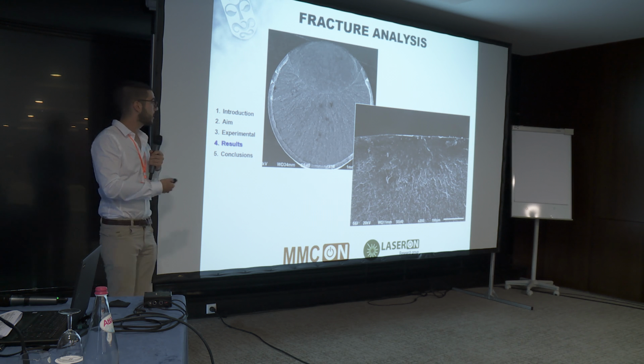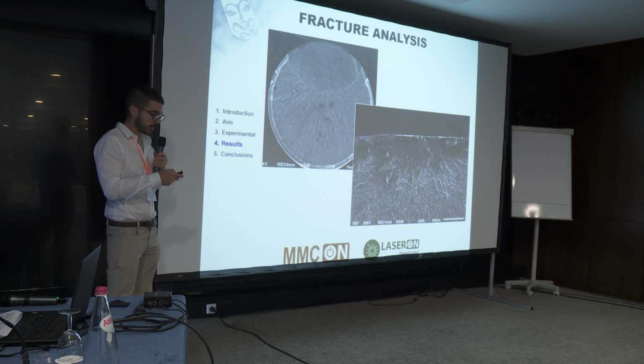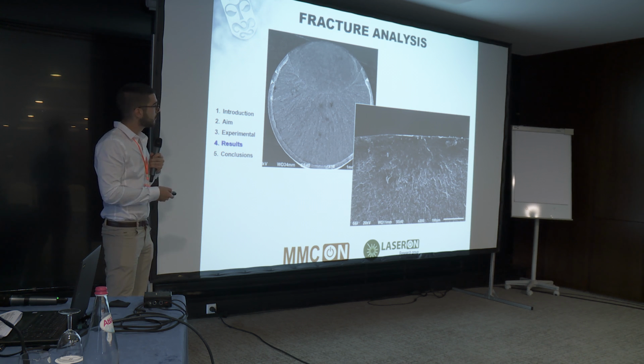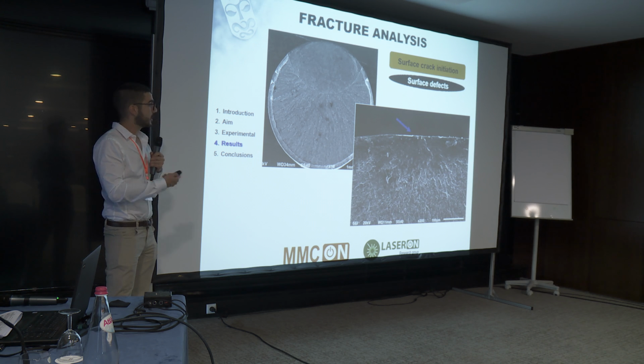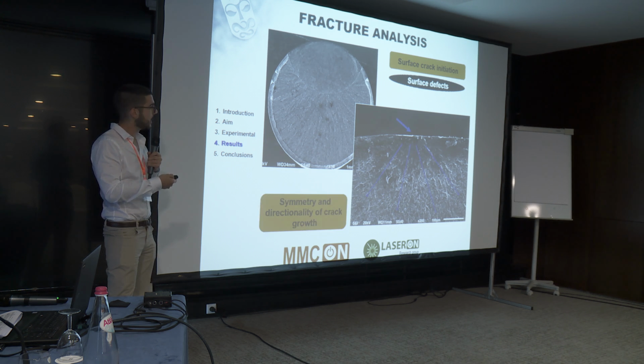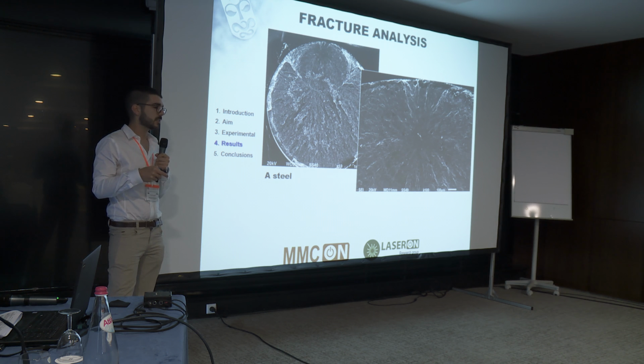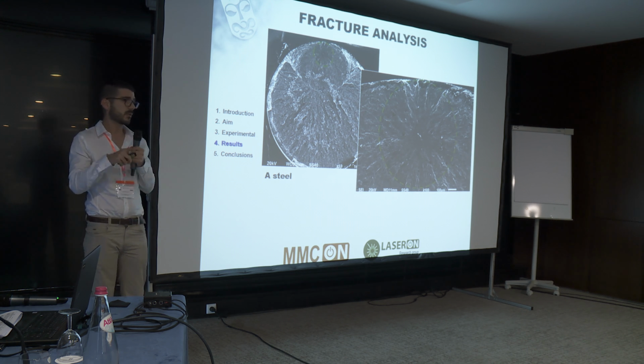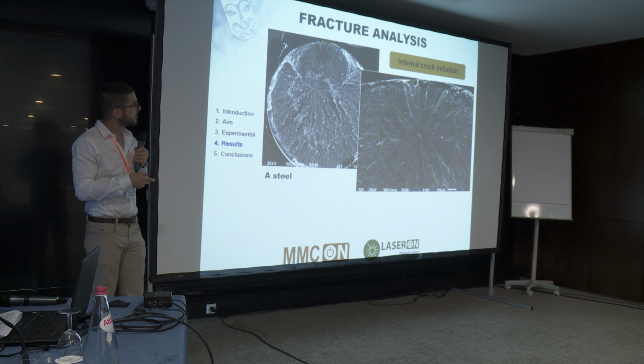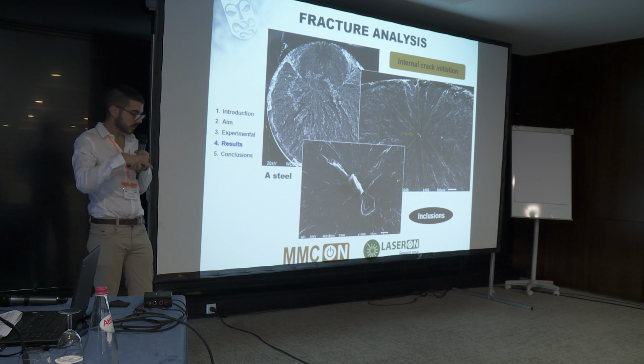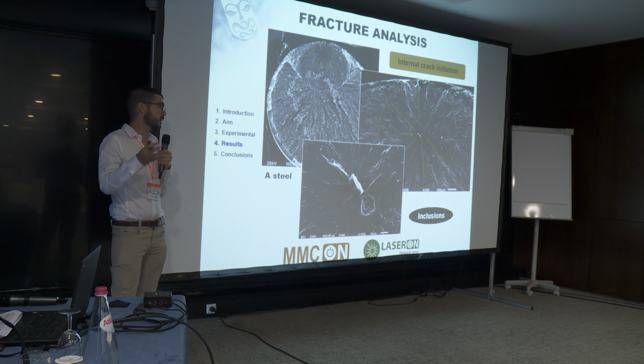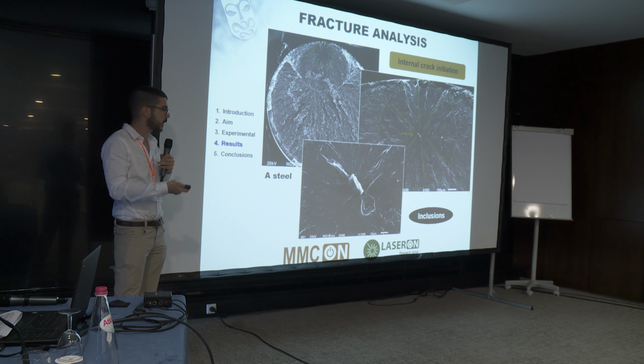And then we also did a fracture analysis through SEM images to have higher magnification images. We can see that, as I said, in most specimens surface crack initiation took place, and we can see it very clearly in this picture. But in some A steel specimens that failed, especially at a high number of cycles, we were able to see the characteristic fisheye region from an internal failure, and in the middle of this circle we could see the presence of inclusions, which were formed through the manufacturing process of the steel.